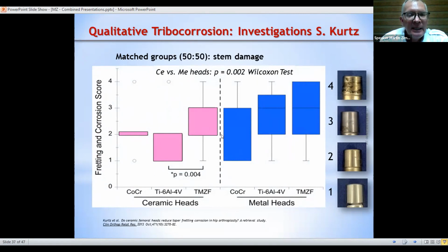On the left-hand side in pink, we have the results observed with the ceramic ball heads, and on the right-hand side in blue, with metallic heads. You can see in general view that the pink is lower than the blue. So qualitatively, we observed less risk of fretting corrosion with ceramic heads compared to metallic heads. Interesting also, within one family, if you are using ceramic heads, it depends on the material of the stem. If you use the conventional titanium, aluminum, vanadium, compared to TMZF, which is also called beta titanium or flexible material, you also have a big difference. The conventional titanium creates less risk of fretting corrosion compared to the beta titanium.